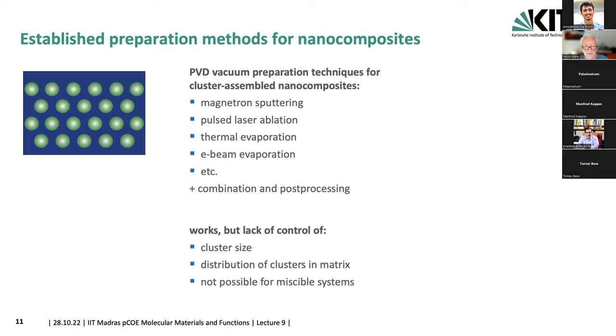The other thing is that it's difficult to control the distribution of the clusters in the matrix. And last but not least, it's not possible for a miscible system. If you take copper nickel and co-deposit it, you get an alloy, a solid solution alloy, for any composition or ratio of the two elements. So this I would call lack of control, which would be nice to have.